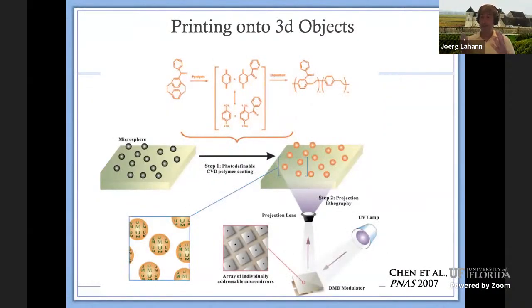Now, the coating itself is superior to a spin coating in the sense that it's conformal and can coat three-dimensional objects very nicely. And to prove that case, we took just a bunch of glass beads, basically, coated them with a particular polymer. This is a polymer that has a benzophenone side group, so it's a photoreactive side group here. So this reacts with light, and then we used 3D projection lithography to pattern onto those glass beads to show the effect of three-dimensional coating. And so this works quite nicely.